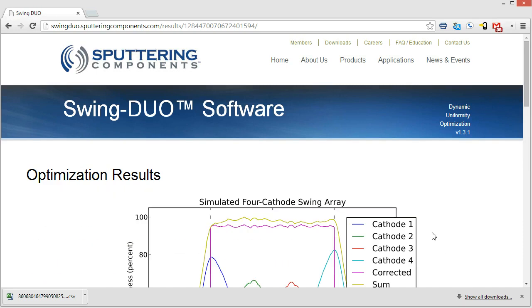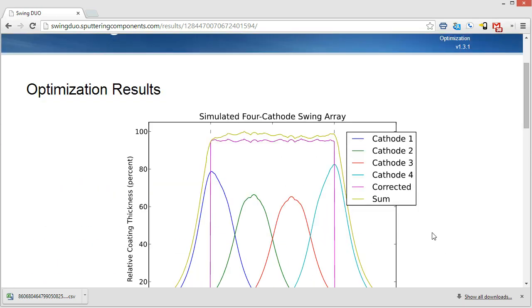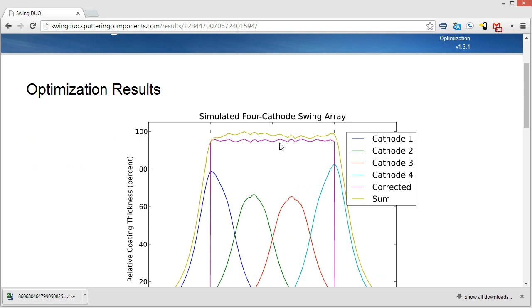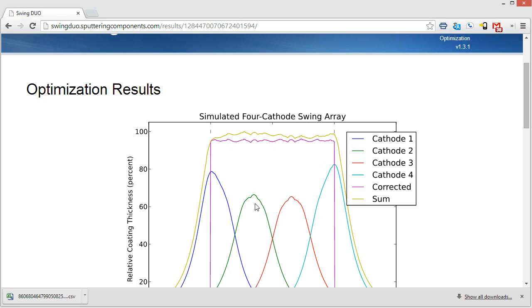All right, there's our results. So you can see the sum of the initial that we had, which was, this is the uniformity that I kind of put in there, overlaid with our initial one. So it kind of just corrected for it. And then this is our corrected uniformity, which is in purple again. So the sum, the sum was our previous uniformity in kind of this goldish color. And then again, all of our individual cathodes. And so here my uniformity went from plus or minus 2% to plus or minus 1.01%.